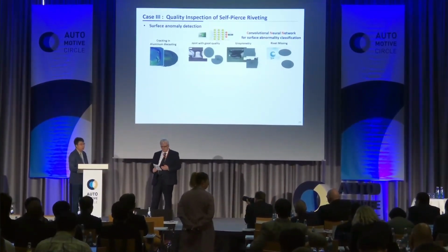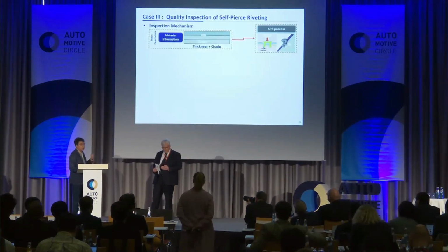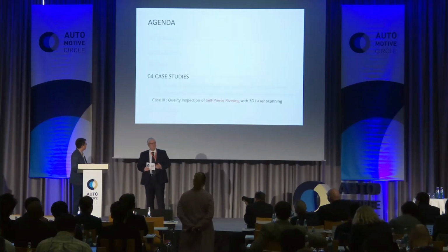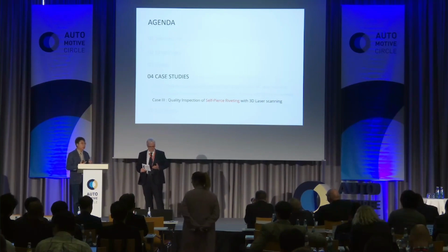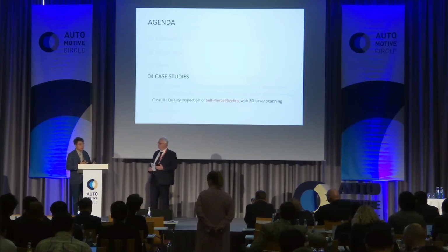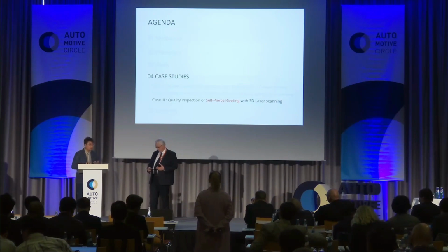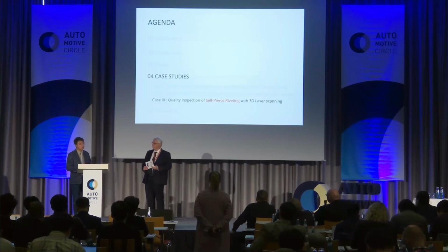Right, very good question. We actually faced those problems. As I mentioned earlier, the top side and bottom side have a brightness difference depending on the panel combination. It actually had different geometry of the indentation. So we have to use a different algorithm for the top and bottom, depending on which plate is on the top and which is on the bottom. And with that, we implemented an algorithm to make the same estimation.